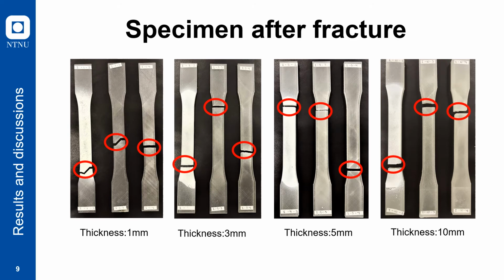And this is how the specimens look after the fracture. As you can see, most of the specimens fractured near the gauge length, and some of them fractured in the middle part. Most of them have a horizontal line for the fracture, and some of them fractured along the raster angles, which in this case we have plus minus 45 alternately for each layer.